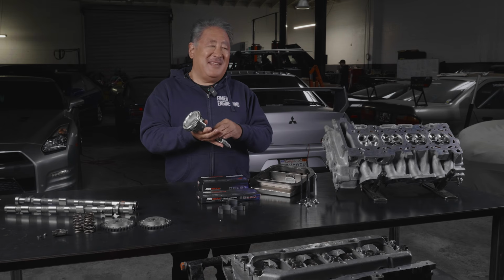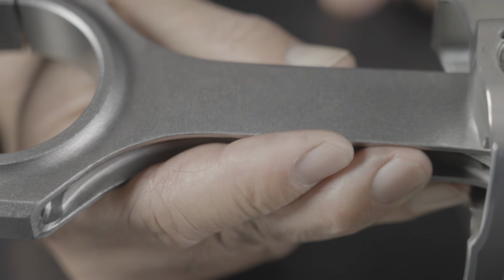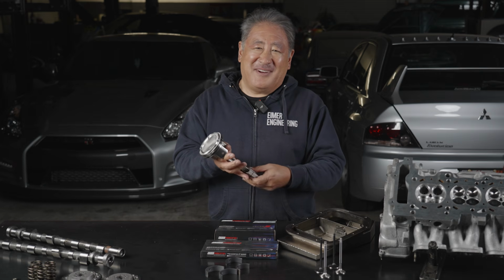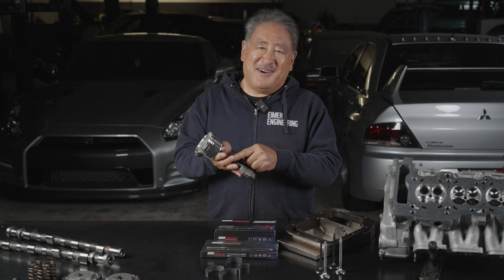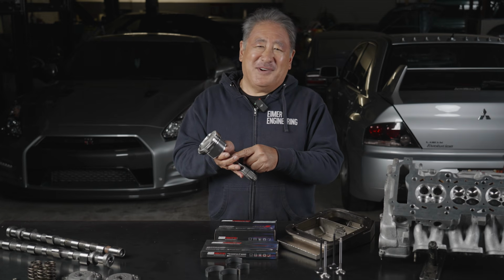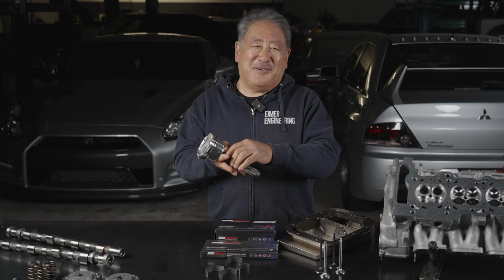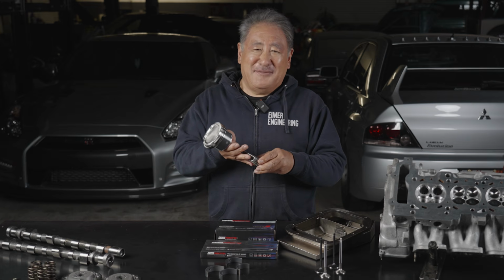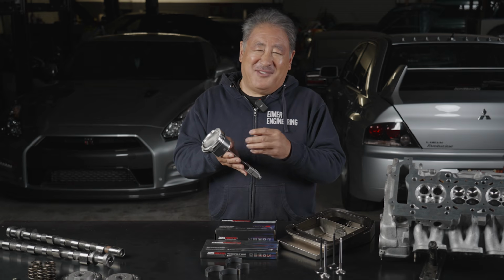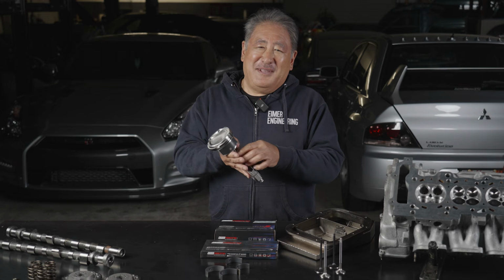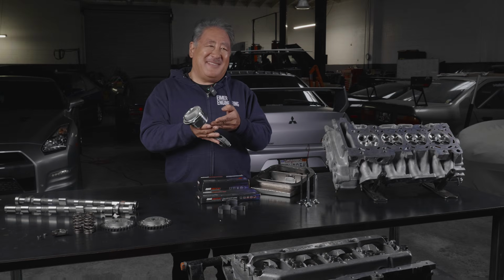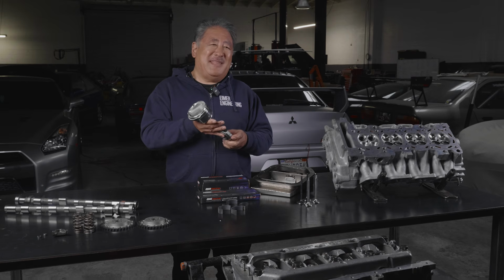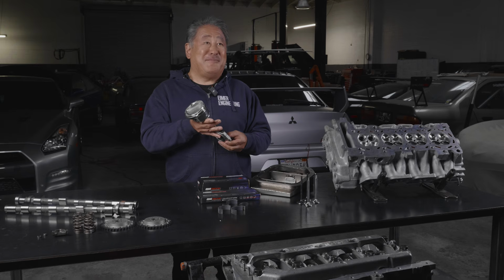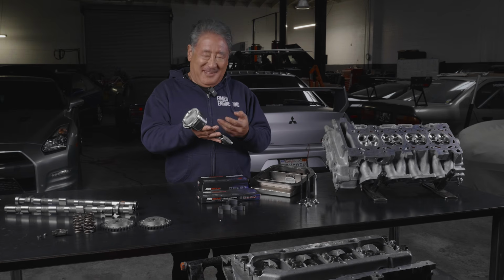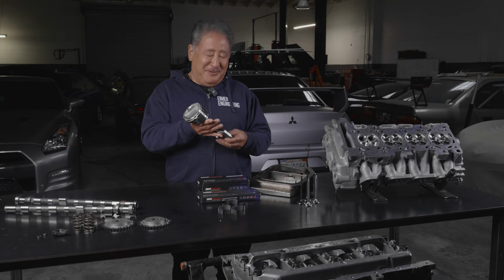The Eagle rod is double shot peened, so it's shot peened with a big shot first to get a compressed layer in there really good, and then with a smaller shot to really refine the grain on the top skin. Now, shot peening is bombarding the metal with spherical hardened steel balls, and this kind of microforges and puts a tough skin on the outside of the part. So you get grain refinement, it shrinks the grain, it toughens it up, and makes a really tough skin that cracks have a hard time propagating in. When you do shot peening, it improves the fatigue strength of the part at least 100%. And in a specialized type of shot peening like what Eagle uses, it's probably closer to 150%.